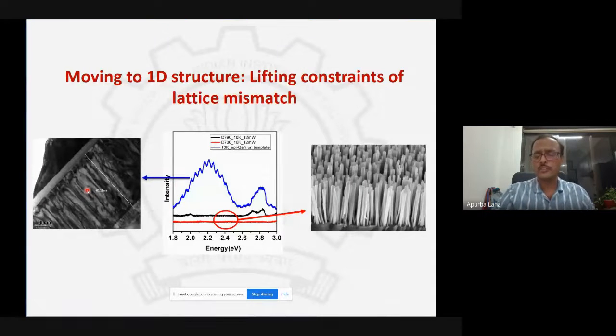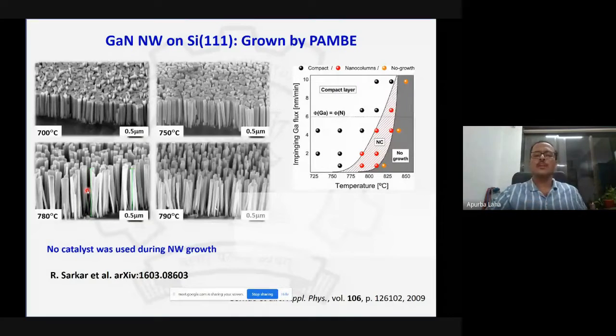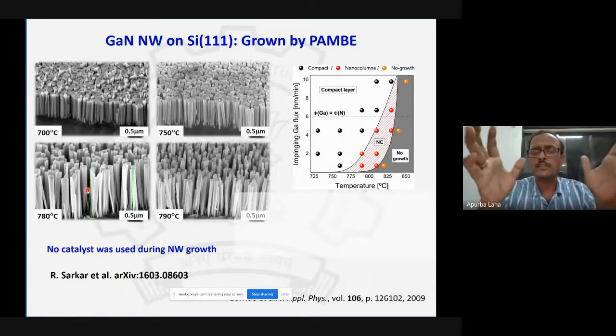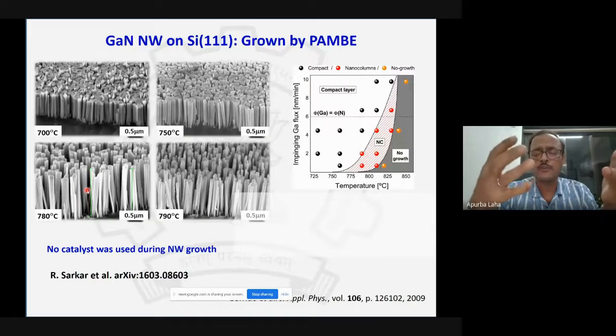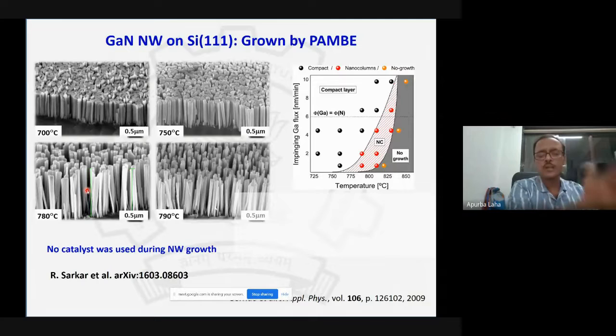One of the ways, as you will see in my presentation, is that we could shift the structure into a one-dimensional form, and this one-dimensional form will have no yellow luminescence. That means structurally they are much more perfect. There are other advantages of having these nanowire or one-dimensional structures. Now, coming to this one-dimensional nanowire, as I said, this is a unique advantage in an MBE system, especially plasma-assisted molecular beam epitaxy. All we have to do is play with the process parameters, change the III:V ratio, and then we can move from one kind of structure to another kind of structure. For example, let me give you the schematic, or the graph, here on the right side.